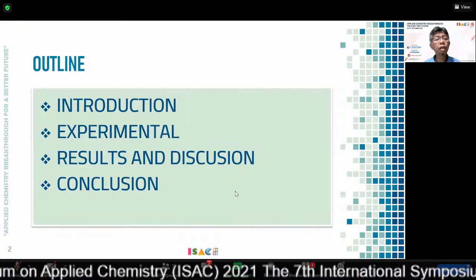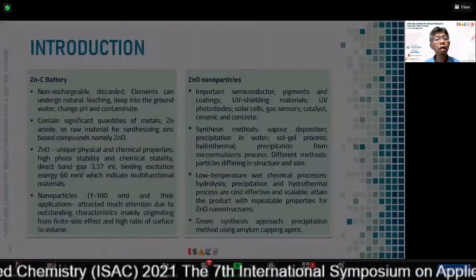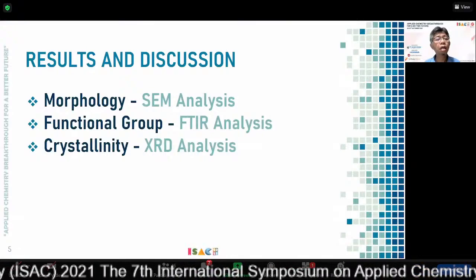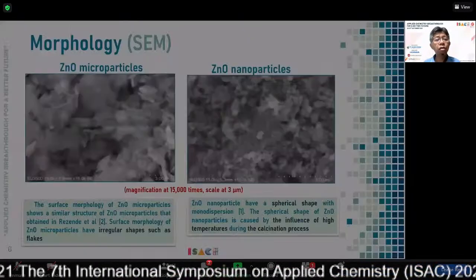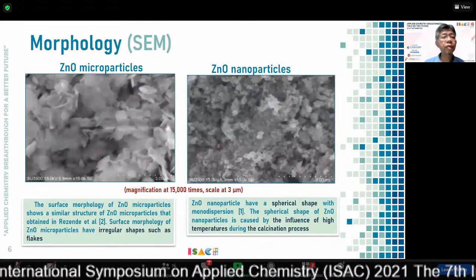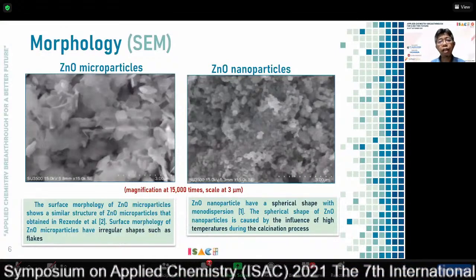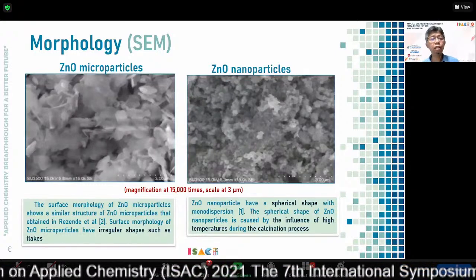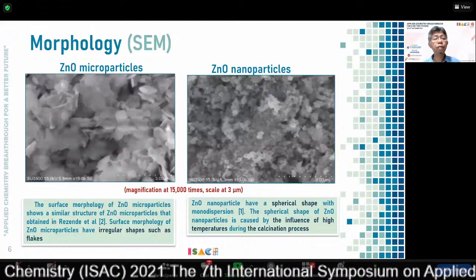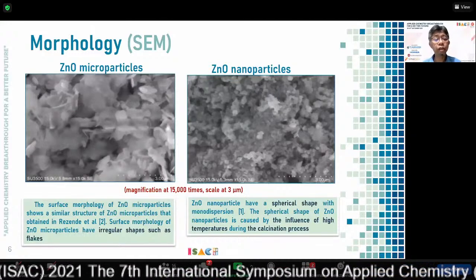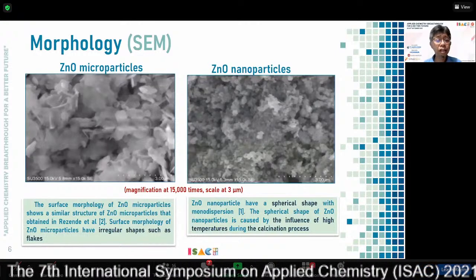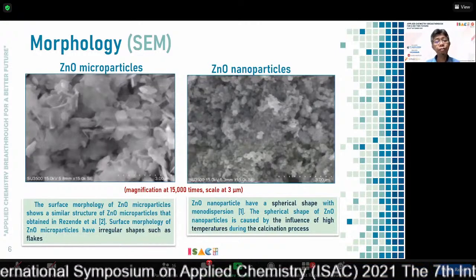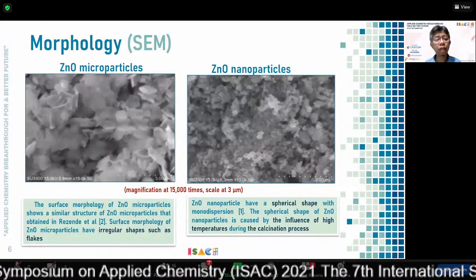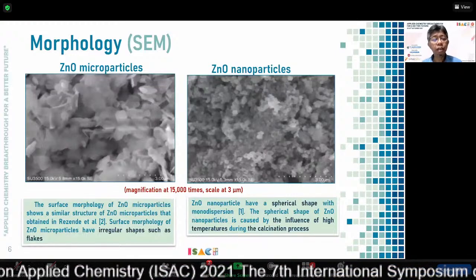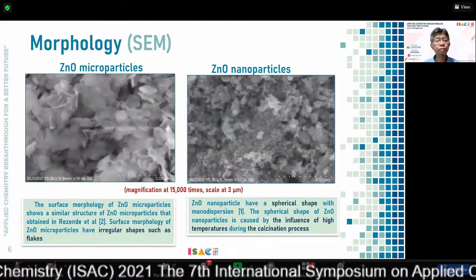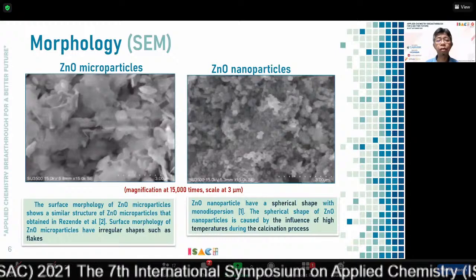If we look at the result here, in the morphology observed by scanning electron microscope, you can look here at the left side. The zinc oxide microparticle shows irregular shapes, like flakes. These characteristics were also found by Rezende and his co-workers when they prepared zinc oxide microparticles.